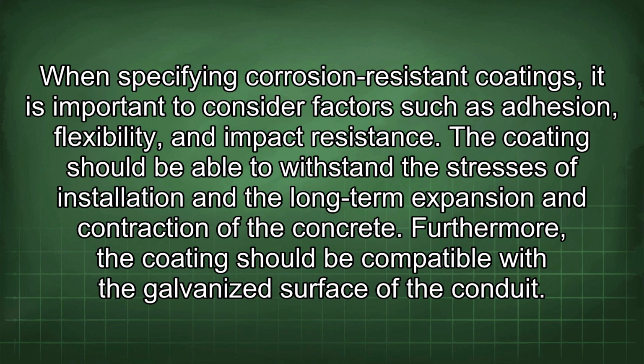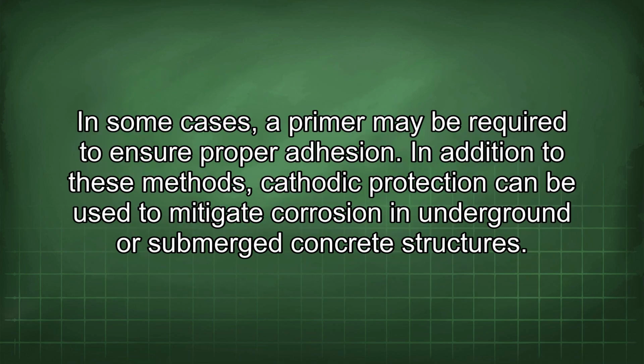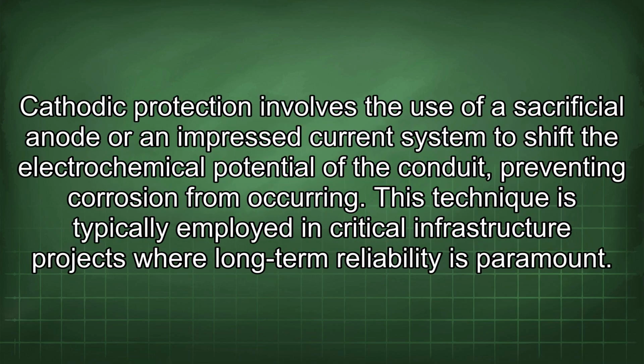When specifying corrosion-resistant coatings, it is important to consider factors such as adhesion, flexibility, and impact resistance. The coating should be able to withstand the stresses of installation and the long-term expansion and contraction of the concrete. Furthermore, the coating should be compatible with the galvanized surface of the conduit. In some cases, a primer may be required to ensure proper adhesion. In addition to these methods, cathodic protection can be used to mitigate corrosion in underground or submerged concrete structures. Cathodic protection involves the use of a sacrificial anode or an impressed current system to shift the electrochemical potential of the conduit, preventing corrosion from occurring. This technique is typically employed in critical infrastructure projects where long-term reliability is paramount.